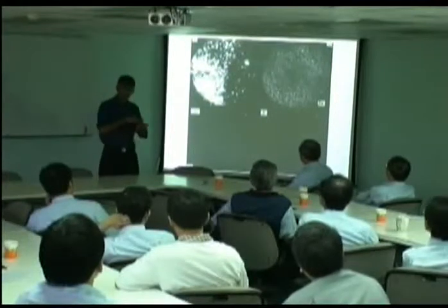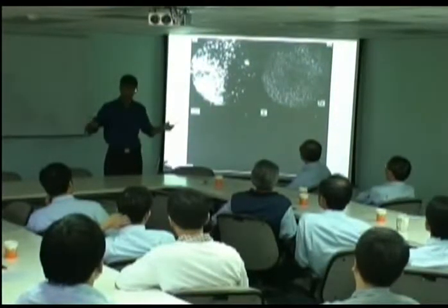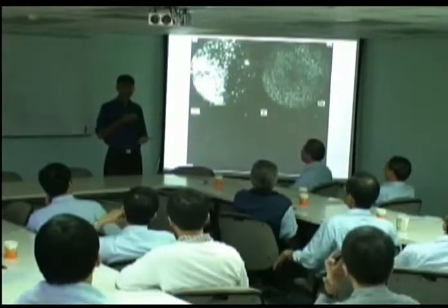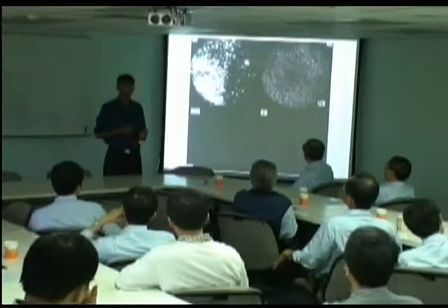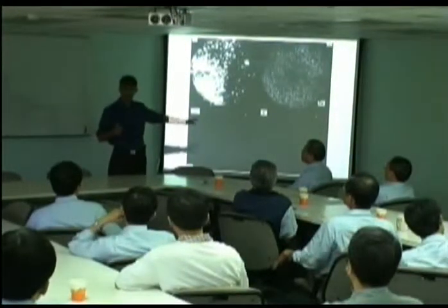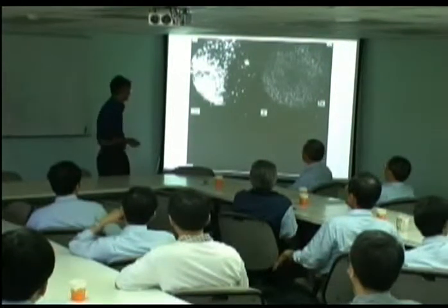Now you can see that the iron atoms and silicon atoms are perfectly homogeneously distributed. There's not even segregation at the interface, because it's a coherent interface. So we can conclude from many, many experiments like this that there is absolutely no partitioning of substitutional solutes on the finest conceivable scale. That means you cannot get a finer scale than this. No question, there is absolutely no partitioning of substitutional solutes during the bainite transformation. Of course, that is consistent with a displacement.